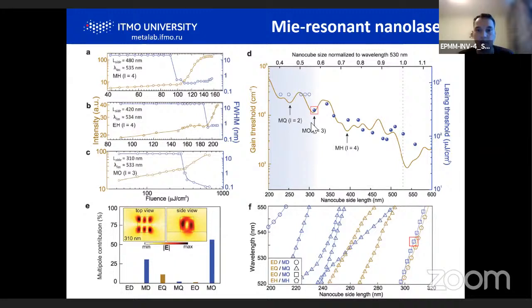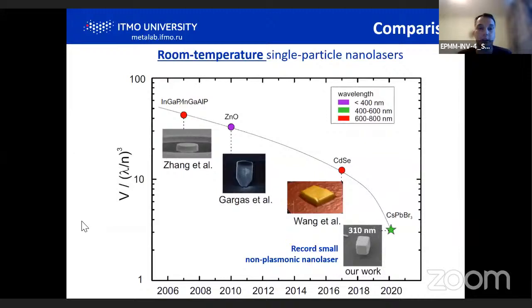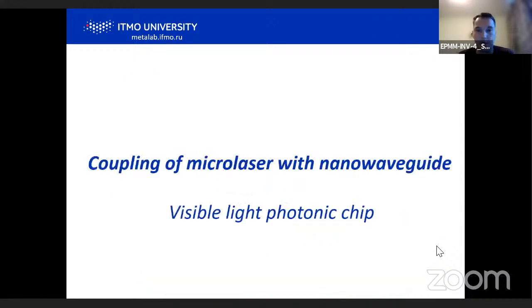And we observed the smallest nanoparticle supporting lasing in the visible range is a nanoparticle of size close to λ/2. And this corresponds to magnetic octupole resonance. This is the result of our mode decomposition. And interestingly, this is a world record among non-plasmonic nanolasers working at room temperature in the visible range, as you can see here. This is because of the very high gain of perovskites.